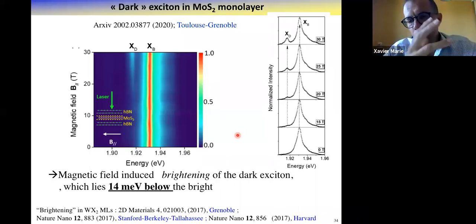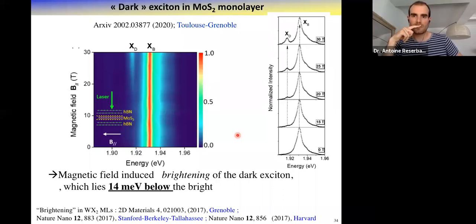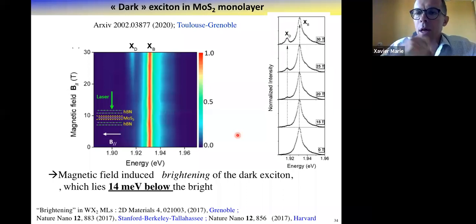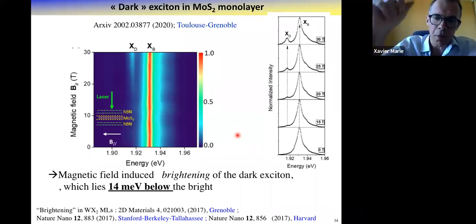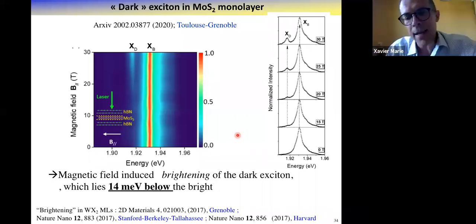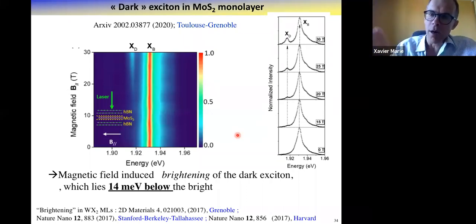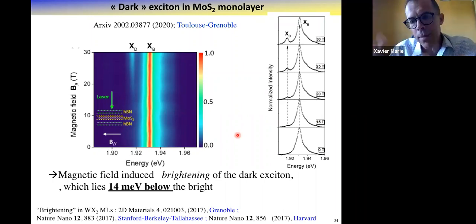And basically it corresponds to our estimate of the oscillator strength difference between the bright and the dark exciton. The dark exciton oscillator strength will come from the spin mixing. When I show the spin up, spin down for the state, it neglects the mixing induced by spin orbit with higher energy bands. And we estimate this mixing to give an oscillator strength, with zero field, 2 or 3 orders of magnitude lower